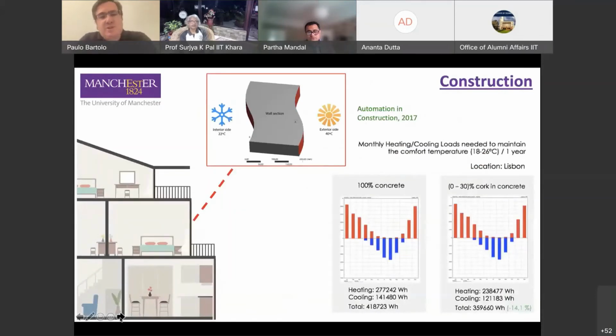And as I mentioned, these strategies allow us to reduce the energy consumption in a building. We run a simulation program, and basically the idea was to investigate the energy consumption of a room in Manchester and Lisbon in different scenarios. One was considering that all the walls were made with 100% concrete, and the second scenario where we have a concrete cork gradient structure. And as you can see, using these functional graded concrete cork building elements, it is possible for a room in Lisbon to reduce the energy consumption in order to keep the temperature in the room more or less constant between 18 degrees and 26 degrees throughout the year.